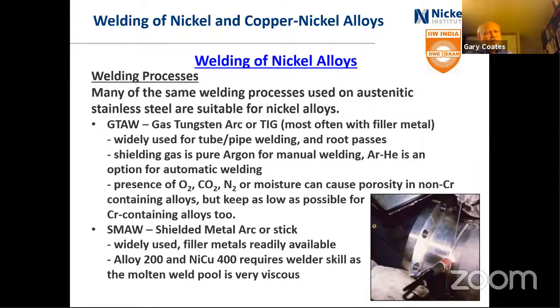Most often, TIG welding is done with filler metal. You really would like to ensure you're adding filler metal there. Of course, if you have very thin material, that may not be possible. But with any sort of thicker material, we would really like to have filler metal added for corrosion resistance and for hot cracking resistance.